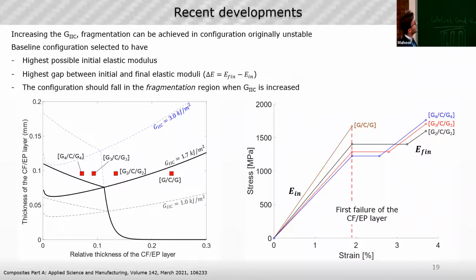Another approach is doing a parametric study in the damage mode map, just changing the fracture toughness of the material. So we are just keeping the same configurations, but acting on the interface and making it tougher. And the toughness also affects the possible scenarios we may have. So if some configurations with the baseline material give us a certain value of fracture toughness, and we hypothesize to have 4 different configurations, these configurations are bad in any case with the damage modes. But if we increase the toughness, we may have fragmentation with some configuration, but how is the question?